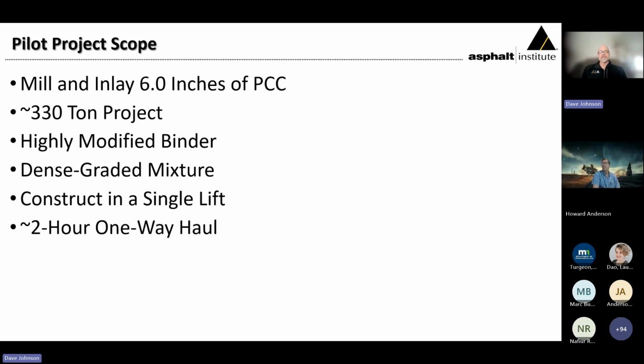All right. And the project itself was a 6-inch single lift. They milled and inlaid some existing Portland cement concrete, around 330 tons, highly modified binder, of course. It was a dense graded 12.5 millimeter Superpave mix, and we'll show you that mix design here in a moment. It was constructed in a single lift, and it's also noteworthy that this is a 2-hour one-way haul.